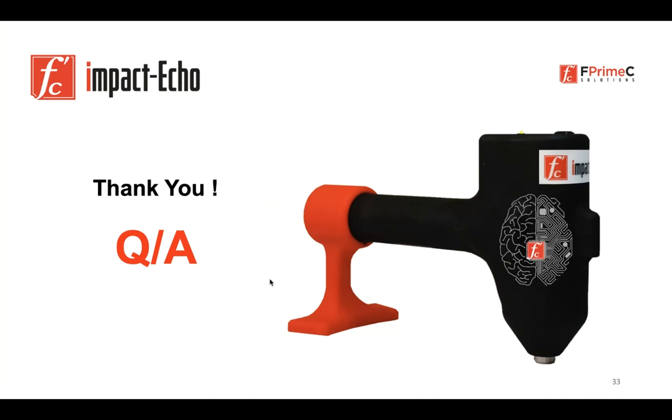Okay, thank you for that, Dr. Farid. Another question is, what additional capability does the Impact Echo test have over the UPV test? The first is that Impact Echo can be used when you have access to just one surface of the structural member. The second point is that you can use Impact Echo to measure thickness. Let's say you have a client for a tunnel lining or abutment walls, and they want to verify the thickness of the lining or the wall, and there is just one access from one side. Impact Echo is a good test to measure the thickness of the wall. Another application is scanning the tendons for post-tensioning structural members. Again, Impact Echo is one of the good devices for that job.